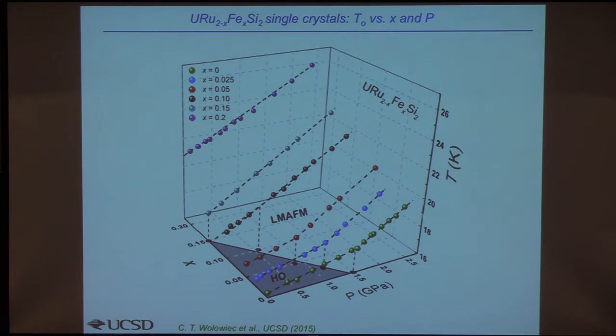And so from that you can deduce a three-dimensional phase diagram of temperature versus pressure versus iron composition, and then if you just extrapolate these points downwards into the XP plane, you can then define a region where you get hidden order and another region where you get large moment antiferromagnetism.